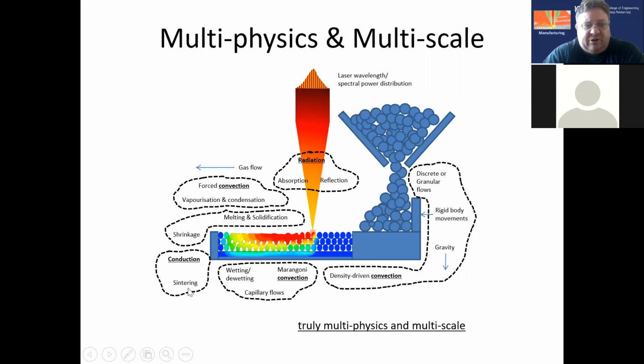So as I said, you've got conduction. When you've got conduction, you've got sintering at neck points, and you can see that sintering happening here in the powder particles. And within the melt pool, this point here, where we've still got a high enough temperature that you've got a molten liquid of metal, there are potentially capillary flows on this small scale. Remember, these particles are only of the order of the same size as the spot size, typically about 70 microns is the spot size. So the particles themselves will have an average size about half that, 35 microns, maybe 40 microns. And at that sort of size, a lot of the capillary flows, the wettability and the surface tension leads to a different type of convection cell within the melt pool.